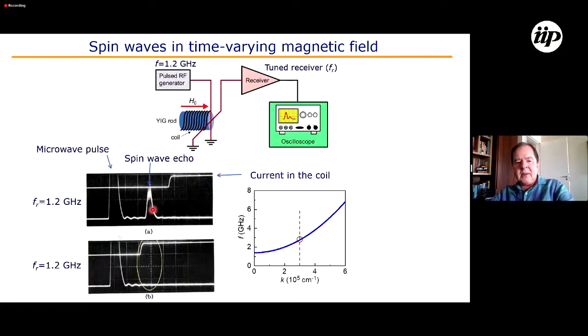The reason it disappears is that as the magnetic field changes to this other value, the dispersion relation comes here, and the spin wave goes with it. In other words, there is a frequency shift of the spin wave, of the magnons. The magnons undergo a frequency shift because the field is varying in time. This happens every time that we have a time variation in the propagating media of any type of excitation. So the spin wave would have another frequency here, so it's not received by the receiver.